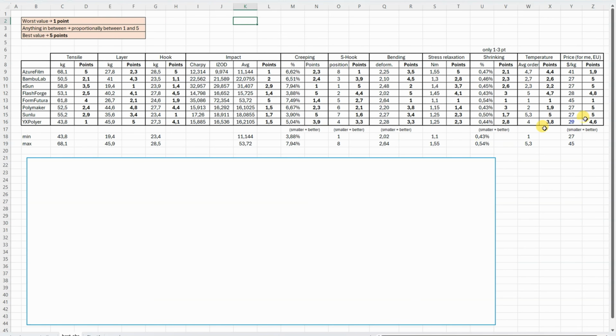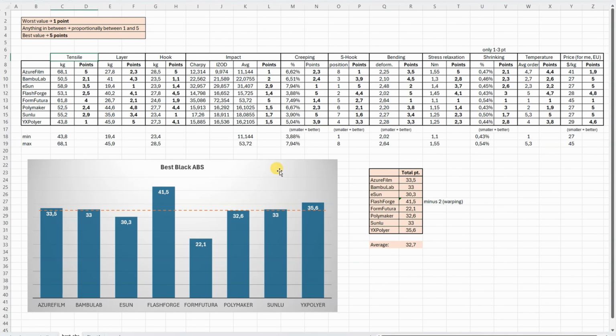In this table I summarized all results. Worst value is 1 point, best value 5 points, and anything between, proportionally between 1 and 5. So this is calculated value. Of course I took into account that sometimes the smaller value is better, and I think only for the shrinking the point was between 1 and 3. To be honest, for the layer adhesion I would give something between 1 and 10, but let's keep it constant. And when I summarize all the results, this is the final score.